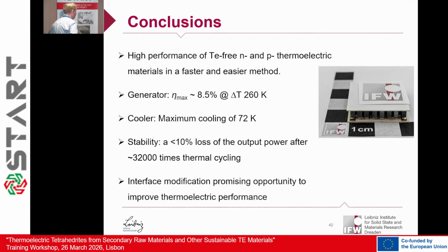Okay, let me summarize my presentation. We were able to fabricate thermoelectric modules from very sustainable P and N-type material. Efficiency is about 8.5%. Internally, we might already have about 9% efficiency in this temperature regime. Cooling performance is also very competitive with bismuth telluride. Stability changes only slightly, about 10%, when we do the cycling for half a year.